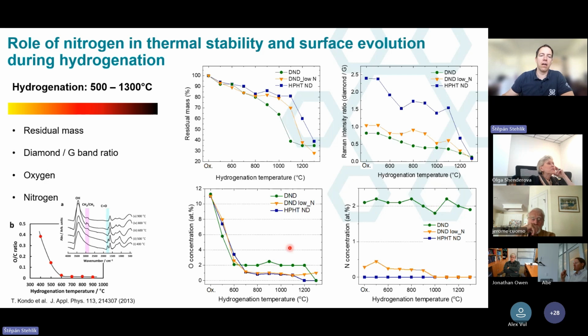Okay, and this is also the oxygen content as a function of the hydrogenation temperature. So with the increasing hydrogenation temperature, we see in DNDs a quite steep decrease of the oxygen, but then the oxygen kind of stabilizes at 2%. This is not oxygen inside, but on the particles, you will see. And in the case of HPHT nanodiamond and low nitrogen DNDs, we got stabilization at about 1%.